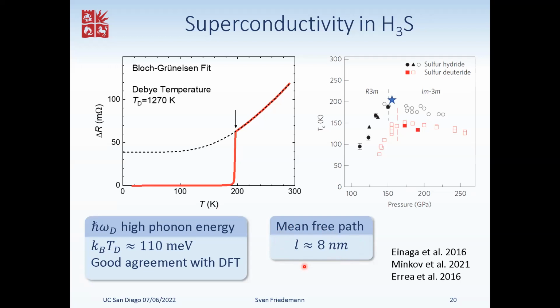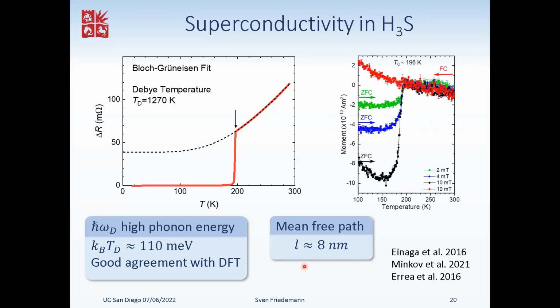Some of the other groups have, of course, also looked at the magnetic measurements. So Michael Eremets' group, most notably, have put the whole pressure cell with a sample, actually designed a specific pressure cell for magnetic measurements, and then synthesized H3S in this and mounted it in a SQUID magnetometer, which does still require subtraction of the background from the cell. But they've done this and they see that there's a diamagnetic signal emerging at the superconducting transition.